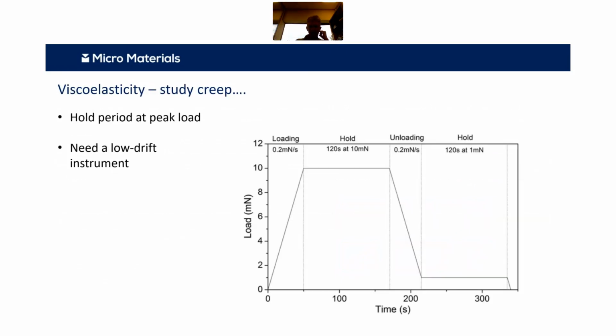So an example of this sort of thing in practice, going back quite a while, is a little study on some polymeric nanocomposites. And here you can see there's a load protocol of something like 300 seconds or so. Most of the test is a hold at peak load, and there's an additional hold at 10% unloading. And this is not for thermal drift correction. This is for looking at creep recovery.